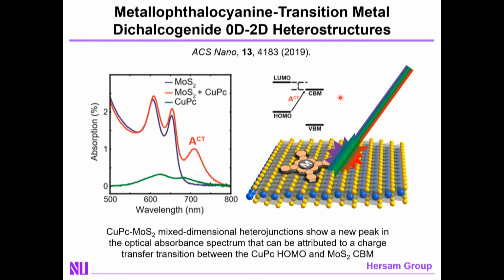But additionally, in this mixed-dimensional heterostructure, we have the possibility of a mixed state between the two sides of the heterojunction, wherein you can imagine charge transfer coming from the HOMO of the phthalocyanine to the conduction band minimum of the molybdenum disulfide. And if indeed this state were to form, then we should see a new peak at lower energy or longer wavelength in the optical absorption spectrum, which indeed is clearly observable as you see here. If we look at MoS2 or copper phthalocyanine alone, we do not see this peak out here at 720 nanometers or so, but it's evidently present in the mixed-dimensional heterojunction.